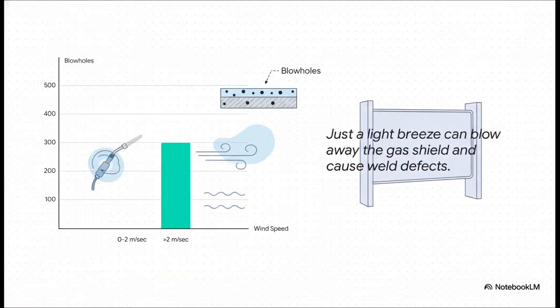And that gas shield, man, is it fragile? Just look at this data. It's pretty stark. A little breeze, something you'd barely even notice, is enough to completely blow that shield away. Once that happens, the weld gets contaminated and you get porosity, these tiny little bubbles or blowholes. That's exactly why you always see welders setting up screens when they're working outside. It's not for show, it's an essential precaution.